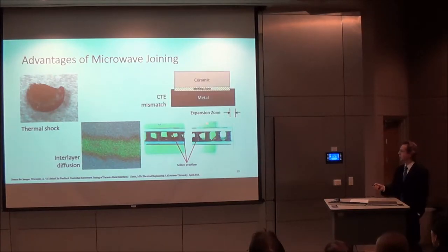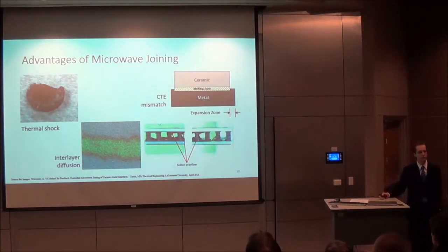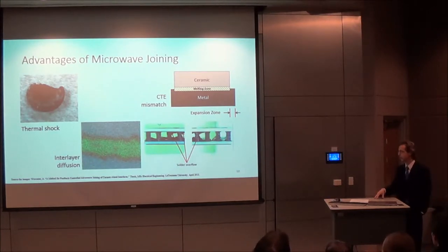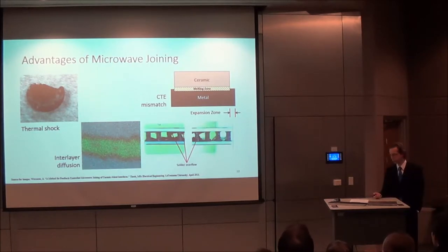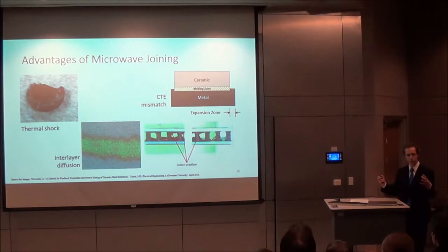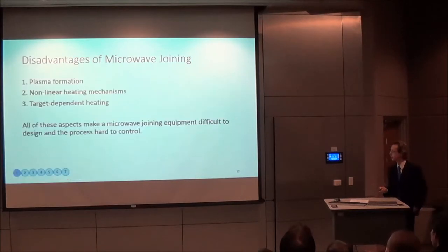In addition, ceramics and metals have different thermal properties and will expand differently as they're heated. And so there's a fundamental mismatch in the coefficient of thermal expansion between them. And when they're heated and joined and then they cool, often the metal will contract much more than the ceramic will, and this will produce stresses at the joint, which can cause failure in the ceramic.